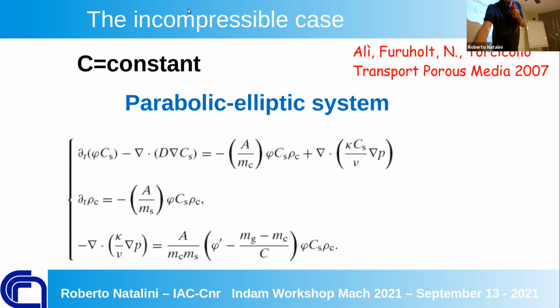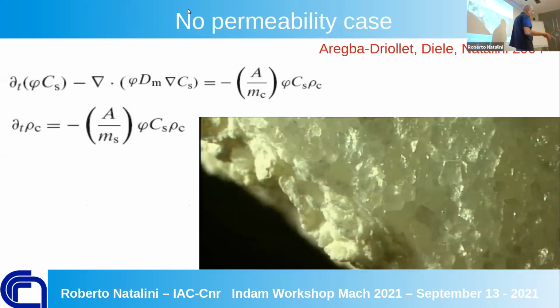But if you take another idea, for marble, where permeability is absent, you can just assume that the permeability is zero. In this case, you can eliminate pressure. And here you have this system which was introduced previously with Aregba-Driollet, Diele and Natalini in 2001. And then it was the basis for many other models that we developed during these years. And so you have this layer forming, and here the marble, as I presented at the beginning. So for marble, this kind of model is much more effective.